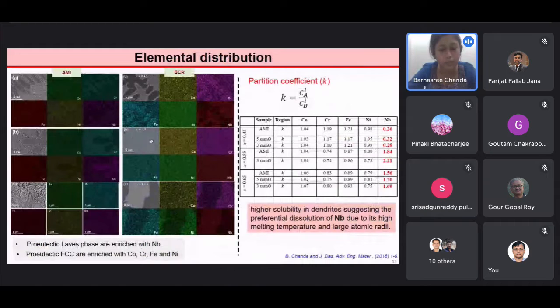The elemental mapping also shows similar results. That is, at 0.45, the proeutectic phase lacks niobium, or very little niobium is present, and at hypereutectic, the dendrites are enriched with niobium. The partition coefficient also shows a higher partition coefficient value of niobium in the Laves phase region, which is due